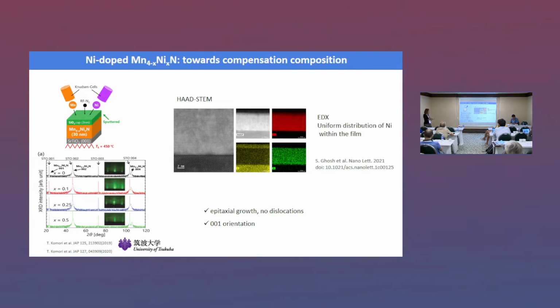So we asked our colleagues in Japan if they could dope the samples with nickel or whatever and try to obtain this compensation. This was done by doping with nickel. They doped the samples with different concentrations of nickel, where x is the concentration in the formula unit, between 0 and 0.20. They managed to conserve a very nice epitaxial growth, 001 orientation, and EDX measurements show that the nickel had a very nice, homogeneous distribution within the layer.